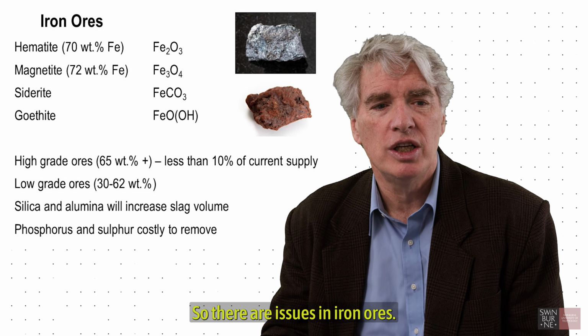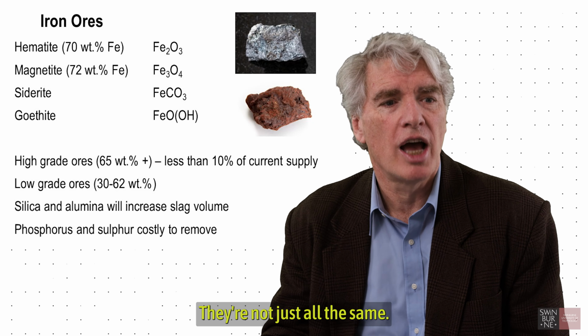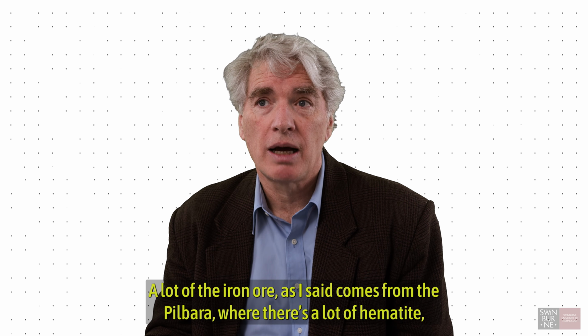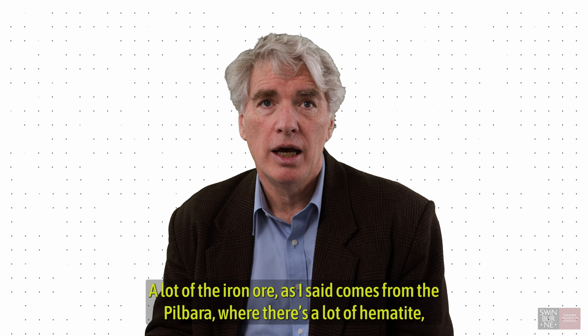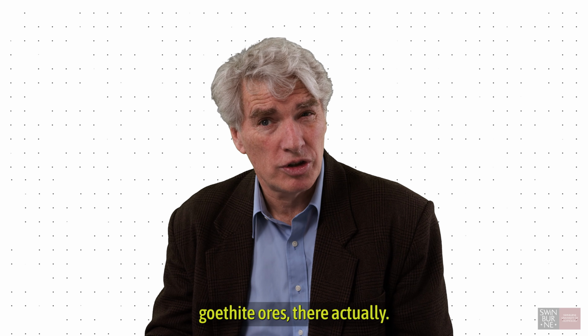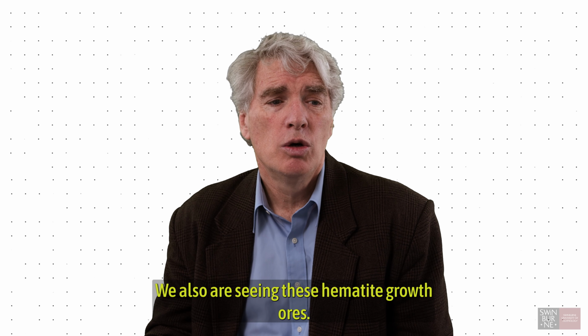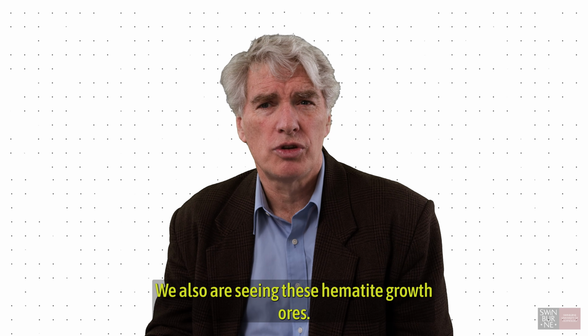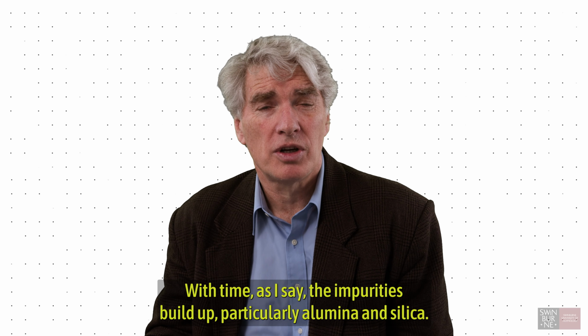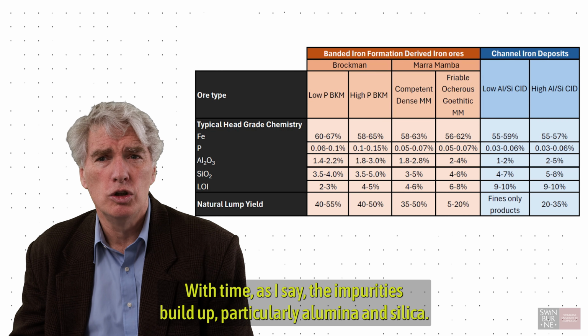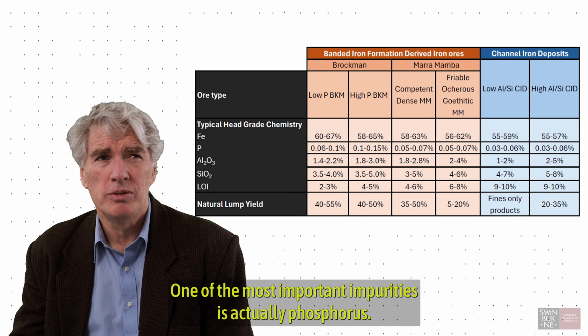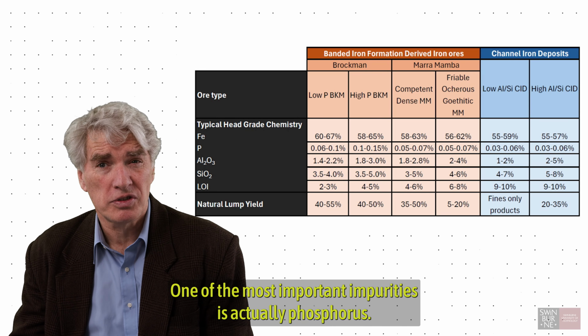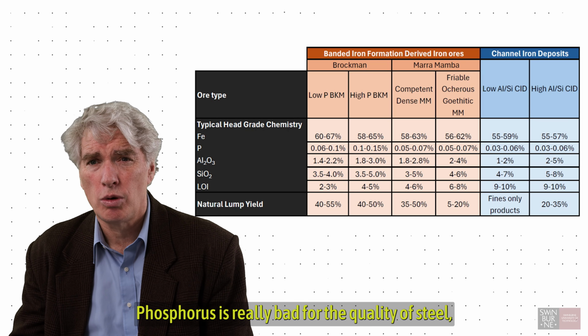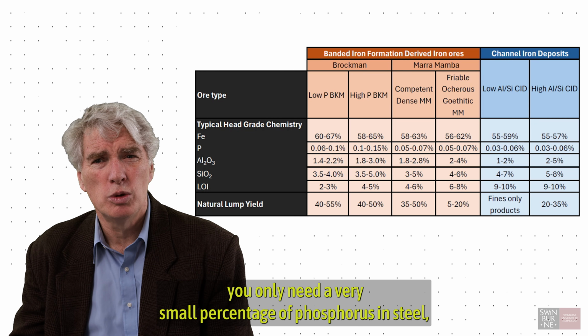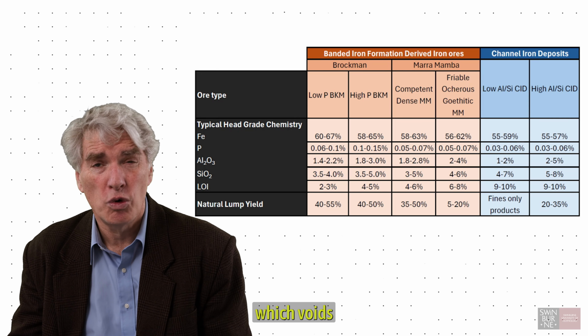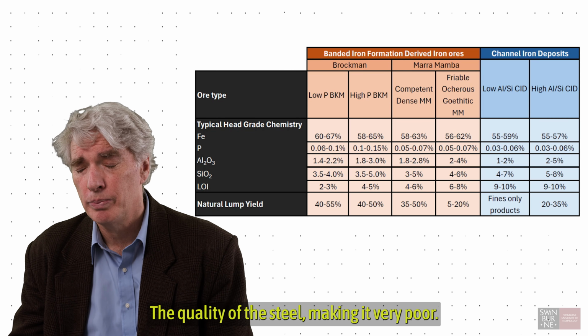So there are issues in iron ores. They're not just all the same. A lot of the iron ores, as I said, come from the Pilbara, where there's a lot of hematite goethite ores. We also are seeing these hematite goethite ores with time, as I say, the impurities build up, particularly alumina and silica. One of the most important impurities is actually phosphorus. Phosphorus is really bad for the quality of steel. You only need a very small percentage of phosphorus in a steel for the quality of steel to be very poor.